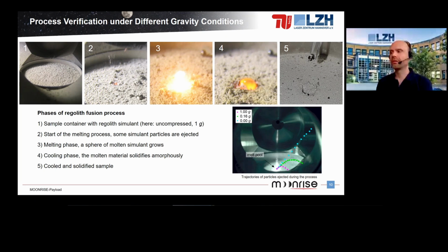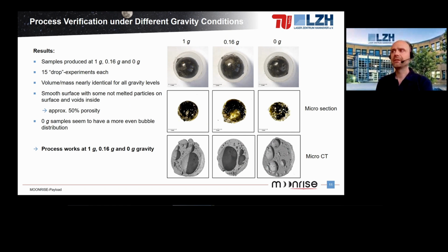So these are the trajectories of the ejected particles, and you can see for 1G there is a different trajectory compared to lunar gravitation, for example. Here you can see a comparison between the different results under different gravity conditions: 1G, lunar gravitation, and microgravitation. We did 15 drop experiments each, and the volume and mass are nearly identical for all gravity levels.